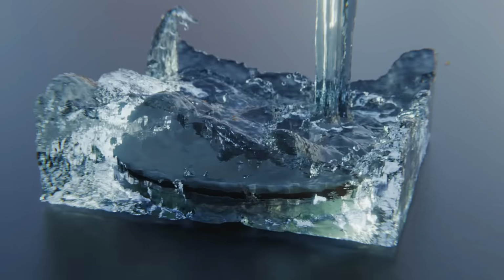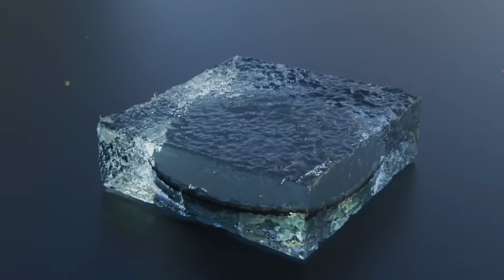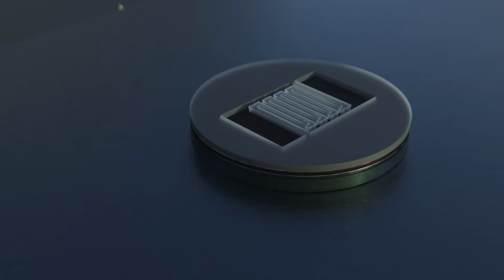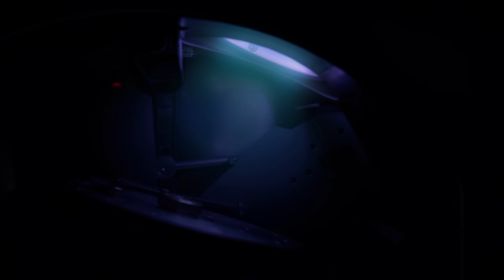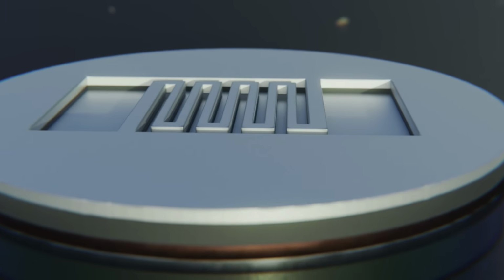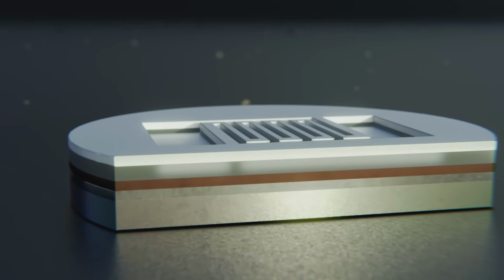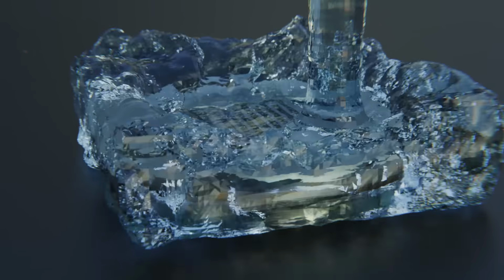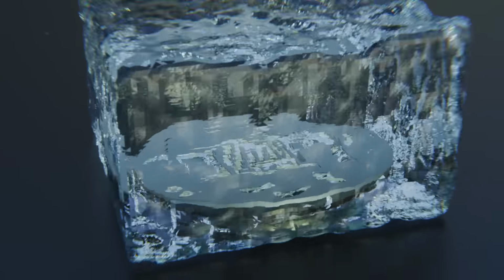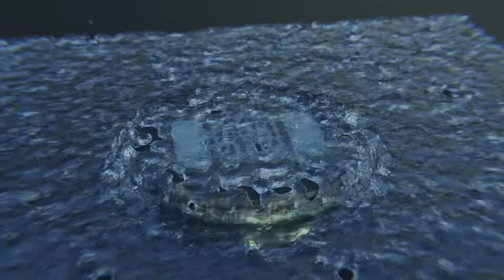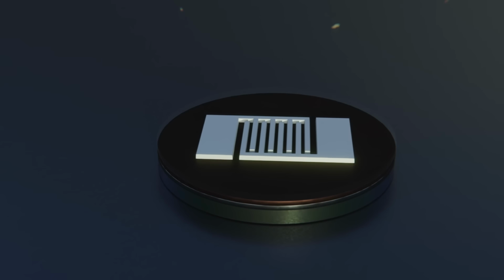After patterning, we use a developer solvent to selectively dissolve the pattern. Then we put it back in the sputter chamber and coat with aluminum. The aluminum will coat the entire surface, but only the regions that have been removed in the developer will have aluminum touching the underlying copper oxide. It's basically acting like a stencil. Finally, we place the chip in acetone to strip off all the remaining resist. The only metal left behind is in the shape of our electrode pattern.